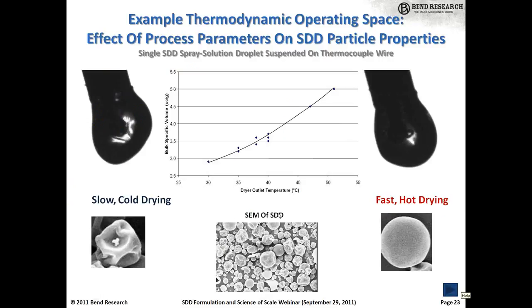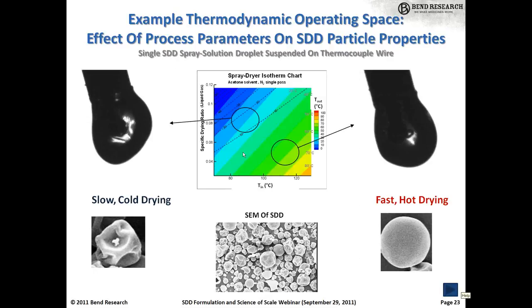As I mentioned, in the simple case of a single pass spray dryer, the outlet temperature correlates very well with the bulk specific volume or density. We recall that we're working with film forming polymers that as the droplets begin to dry, they form a skin which acts as a barrier to solvent diffusion from the interior of the particle to the outside. And we'll show a couple of high-speed camera movie clips showing a spray solution droplet suspended on a thermocouple and then exposed to different drying temperatures or outlet conditions.